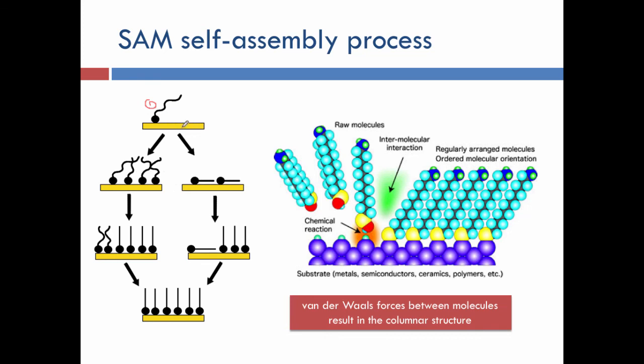And then from there, there's two paths that could happen when more of this molecule's friends come along. Now, they could come in a very dense way, and then what you, I hope, can see is that eventually the heads of those groups would be the only things that could attach to the surface if the density was enough. And then eventually, if enough of them connect to the surface, then the tails are going to stand up. And then it's going to wind up being a very nice, strong forest of these molecules. But the other path is, of course, where there's a low density initially, and then the tails actually lay down.